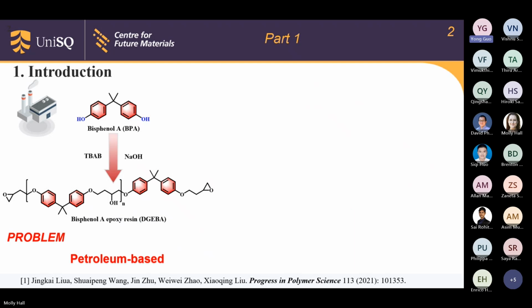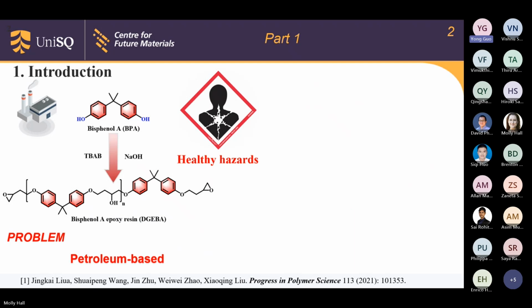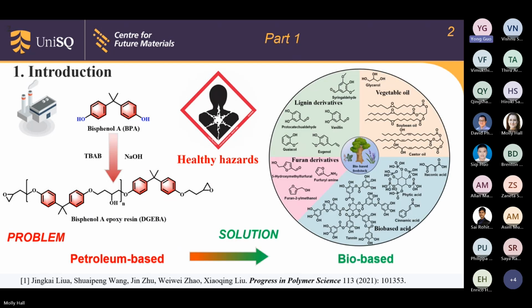I mentioned that the CFRPs consist of polymers such as DGEBA. However, the problem is that basically all of the commercial epoxy resin is sourced from petroleum, especially bisphenol A, which can cause health hazards. So, what can we do? The best solution is to use bio-based feedstocks to replace the petroleum-based ones.